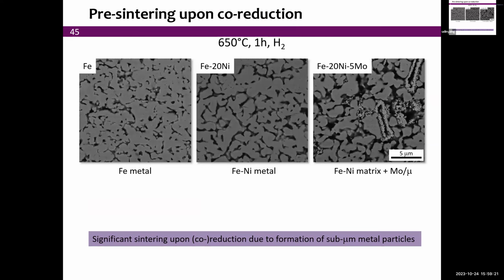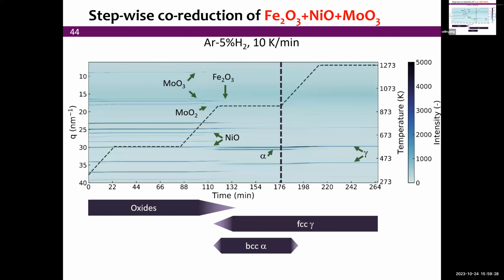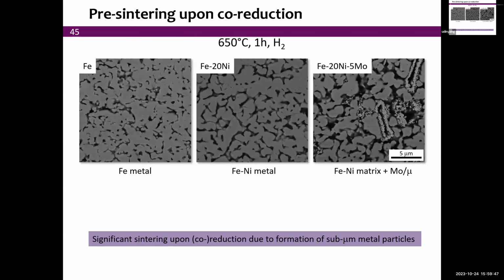So let's have a look at the metallographic situation. At the end, I should maybe go back. At the end of our pre-sintering stage, so here we burn out at about 300 °C. Then we are reducing from the oxide to the metal, but there's also pre-sintering happening. And if we interrupt at this point and cross-section and look at the material, we see that iron, iron nickel, and iron nickel moly all show different levels of pre-sintering.